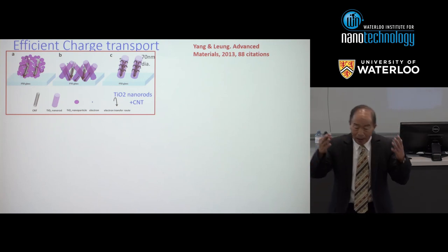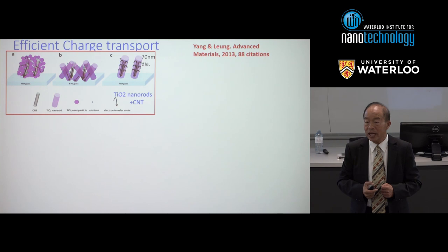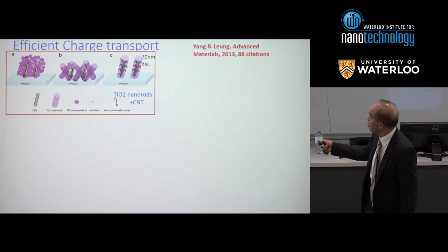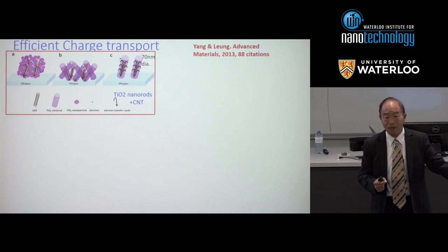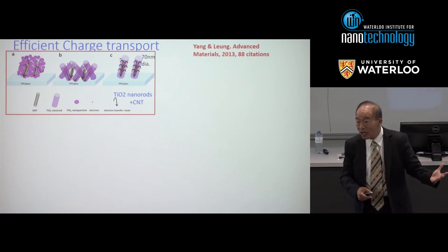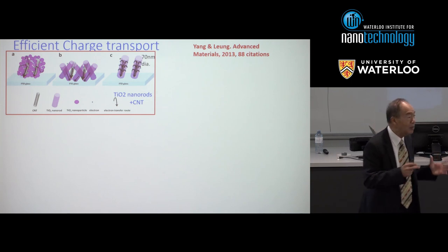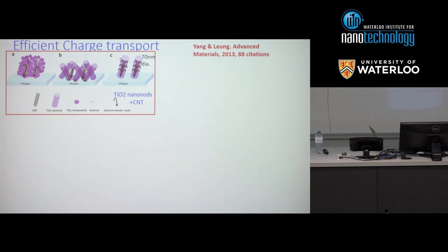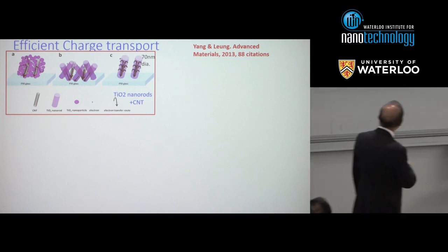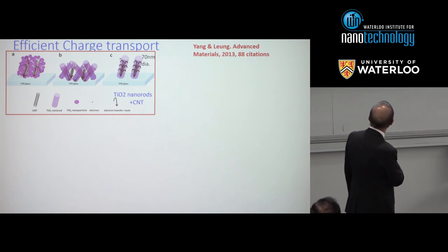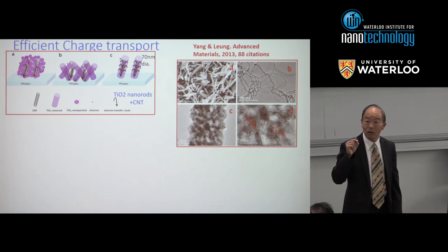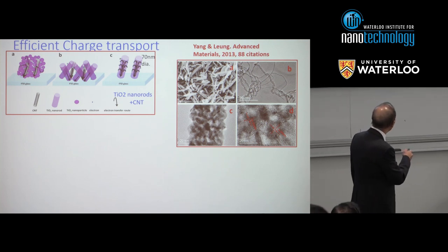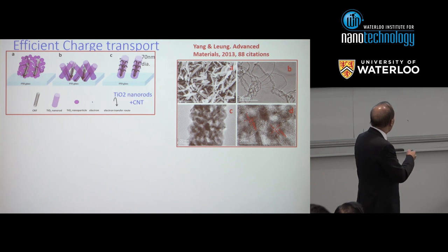The third technology: after harvesting light, we want to transport the electron effectively. The electron typically gets lost. What if we use carbon material inside the nanofibers? We insert a CNT inside the nanofibers — CNTs with diameter about 10 nanometers — so the CNT is fully encapsulated rather than exposed. The nanofiber surface is also not smooth; it has crystallized features of about 10 nanometers, increasing the surface area for dye absorption.